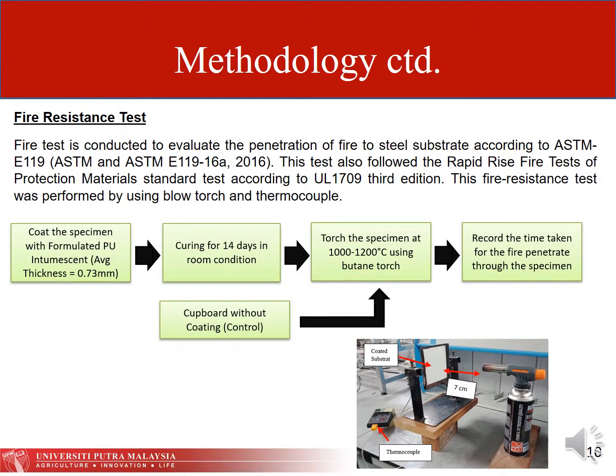Fire resistance test. The fire test is conducted to evaluate the penetration of fire to the substrate according to ASTM E119 and follows UL 1709, third edition. The fire resistance test was performed using a blowtorch and thermocouple. As we can see in the picture, the setup is as the figure shows.